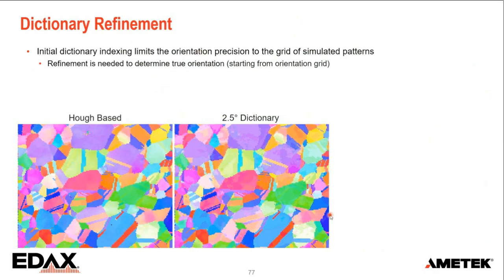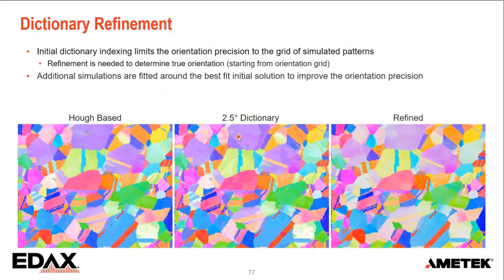And instead of calculating these hundreds of millions of patterns, we can just look at the measurement based on a coarse dictionary, and then just calculate simulations just around that measured point. So instead of having it for entire orientation space, we are just doing a very small local orientation refinement based on the starting orientation we got from this coarse dictionary. And when you do that, you can get really nice refined solutions where we lose these jumps and we get a continuous color scale with, depending on how fine you want to refine, let's say 0.1, 0.2 degree orientation precision.